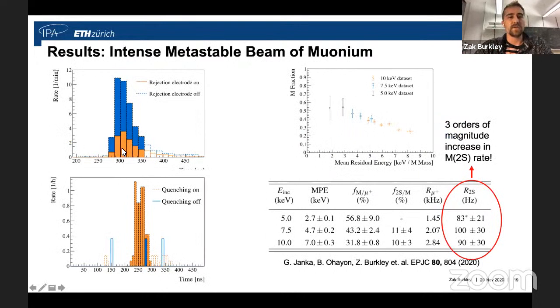Here is a plot of one of our measurements with the rejection electrode on in the orange and the rejection electrode off in the blue. And this is how we could determine the muonium fraction for different incoming muon energies. And we see here it decreases at lower energies, but thanks to the low energy muon beam line, we're able to get down to 4 or 5 keV muon beam. And there we're getting almost 50% conversion efficiency to muonium.